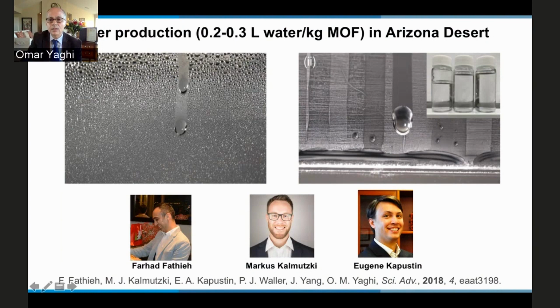This is as much as a small bottle of water. And it turns out that we're not using the entire MOF because our MOF was used as a cake. So air wasn't able to diffuse all the way down through the entire cake. And so there was a need for modifying the form factor of the MOF. But the water you get is ultra pure. It's just distilled water, and you can't really drink it on a routine basis. You need to mineralize it. But this student sent me a video of him drinking the water.